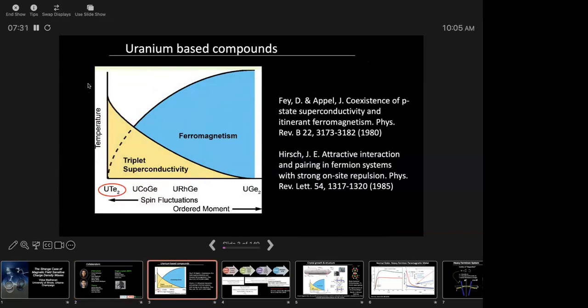Okay, so why are we interested in uranium-based compounds? Primarily because we've known for a very long time that if you want to look for triplet superconductivity, and we're interested in triplet superconductivity for a variety of reasons, including the fact that if you have the right symmetries and the right Fermi surface, some of them might be topologically non-trivial. So if you're interested in triplet superconductivity, one of the best places to look is in the vicinity of ferromagnetic fluctuations. And uranium-based compounds, as you know very well, many of them have ferromagnetism, and many of them have shown to become superconducting under pressure or at very low temperatures. And UTe2 also belongs to this class of materials. And actually, the nice thing about UTe2 is that it has no static ferromagnetism, and it has a whole bunch of magnetic fluctuations. So sort of a very nice candidate for triplet superconductivity.